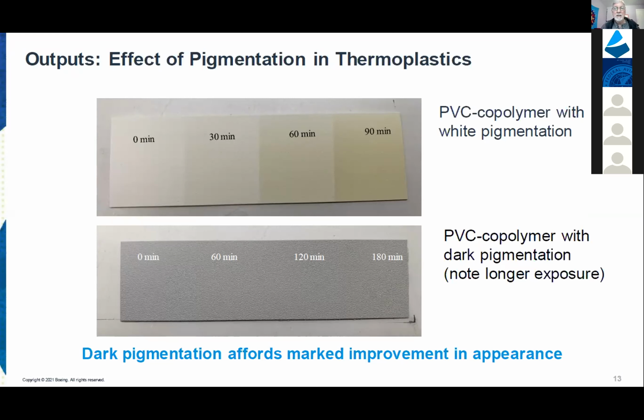Typically, and here's the PVC copolymer. This is a material used in our tray tables. And if you used a white pigmented tray table material, you saw under 222 nanometer exposure, really severe yellowing only after an hour and a half. If you take that same tray table material and you incorporate a dark pigmentation, look at the change. We even doubled the exposure times. We wanted to see what the rate was over a short period, and that's why this slide is in there.